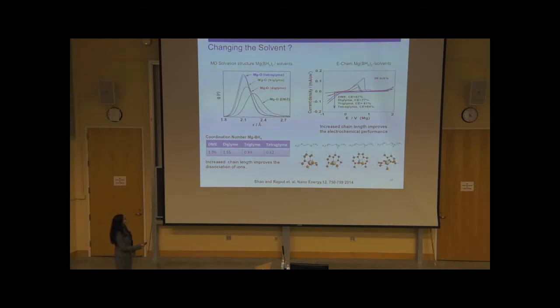And our experimental collaborator studied the effect of this increased dissociation between cation and anion and found that you can significantly increase the Coulombic efficiency simply by changing the solvent and increasing the chain length of glymes, because for these higher glymes, you have more oxygen donor density and they can easily separate magnesium from the salt anion.